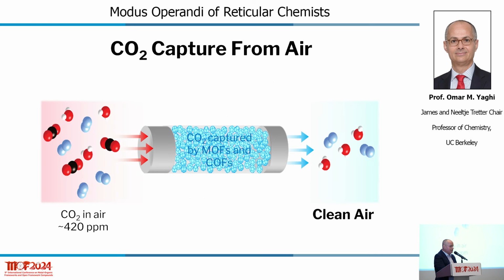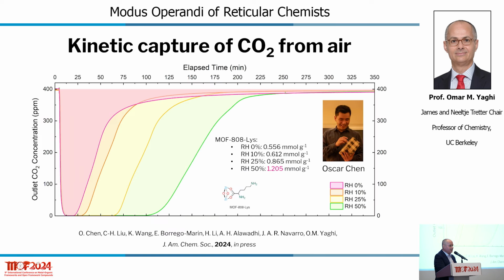Okay, so this is the experiment that many of us, such as in my group or Jeff Long's group or Omar Farha's group, in many of our groups, we try to do, which is that you have a material, you think it's a good material, you expose it to air, and you see whether it takes up CO2 or not. And so this material that I just showed you, as soon as it's exposed to air containing 400 ppm,